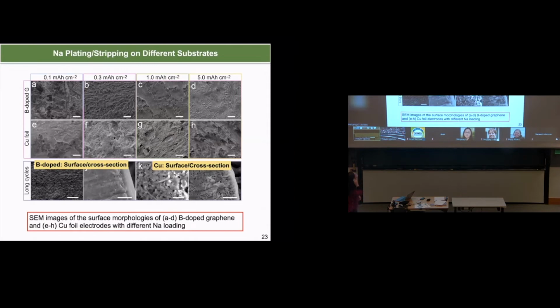Here I want to show another image. I specifically picked the boron doped one because it shows the best electrochemical performance. I would like to draw your attention to the cross-section view of the sodium plating. This is a cross-section view of sodium plated on a copper surface, and this is a cross-section view of sodium plated on a boron doped surface. You can see this shows a very packed and dense sodium plating pattern. But if you look at copper, it is a very porous or dendritic structure, which is especially revealed from the cross-section view of the electrode.